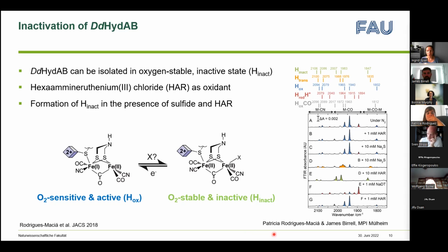There is a very nice experiment performed by my lovely collaborators, Patricia and James. They used hexamine ruthenium chloride as an oxidant and treated the enzyme in the presence of oxidant and a sulfur source. What they were able to show using FTIR spectroscopy is that, starting from H-ox, the active oxidized state, if they treat the enzyme with only oxidant, we don't observe a lot of changes. If they add a sulfur source by itself, sodium sulfide, we also don't see any changes. The enzyme is still in the H-ox state.